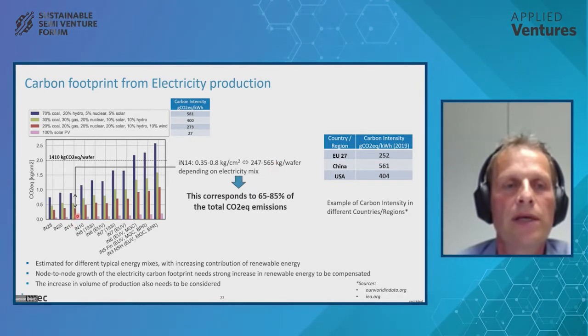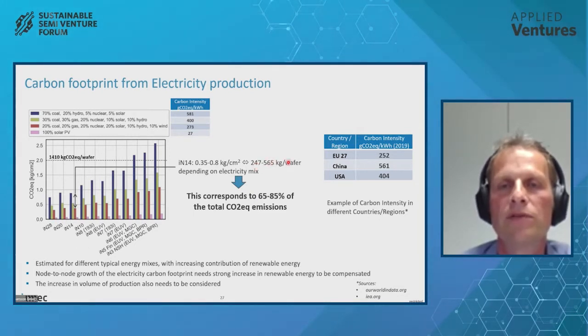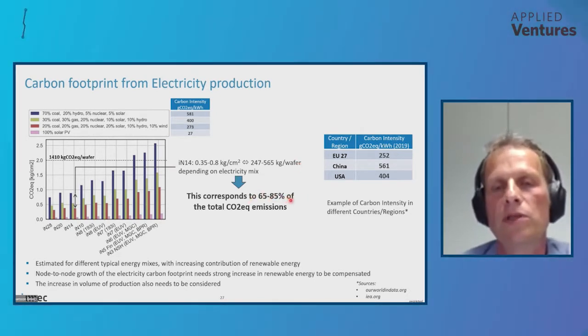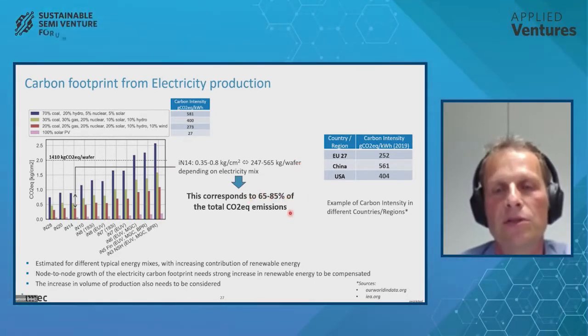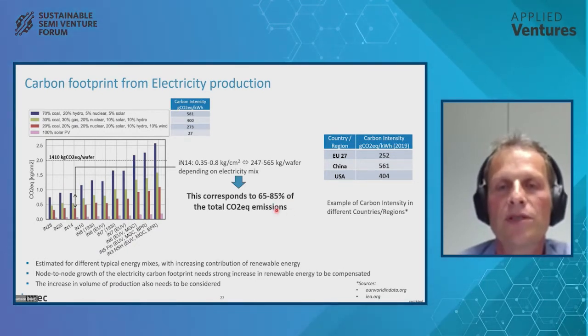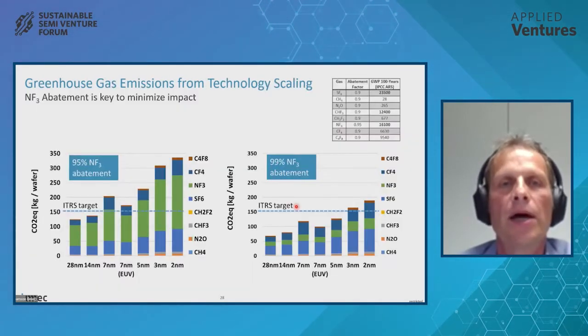What we can say here is that for example, at 14 nanometer, there is about 247 to 565 kilograms per wafer of CO2, depending on electricity mix. And this corresponds to about 65 to 85% of the total CO2 equivalent emissions. Then you might ask, what is remaining? And that's the direct emissions.